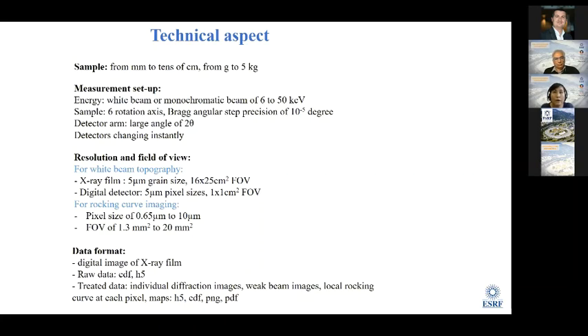Also, for the quality of the data, the resolution and the field of view for the white beam topography, we can have either X-ray film of 5 micron grain size, with a centimeter square field of view. Or starting from next year, we can have a digital detector, which has the same size but a smaller field of view. For rocking curve imaging, we have a very high resolution, with pixel size from 0.65 micron to 10 micron, and field of view from millimeter to 20 millimeter square.